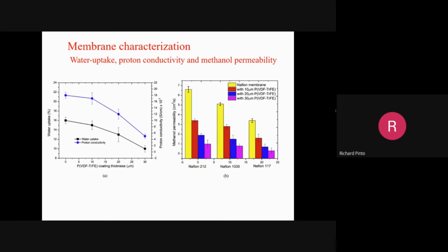Why is water uptake required? Because humidification of the membrane is important for two reasons: to enhance proton conductivity and to enhance the lifetime of the membrane. If the membrane is dry, proton conductivity will be low and membrane lifetime will also be reduced. So you need humidification of the membrane, so we study water uptake. There is a certain formula, I won't go into the details. Water uptake is defined as the percentage of water taken up by the membrane in terms of its weight. This is basically the simple definition.